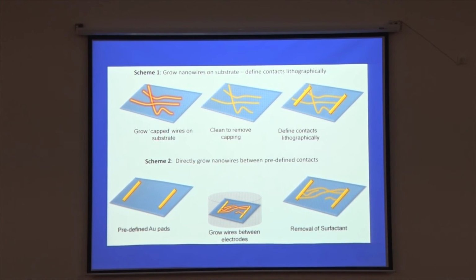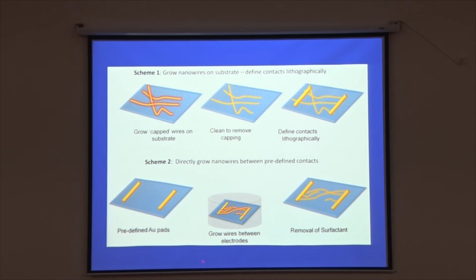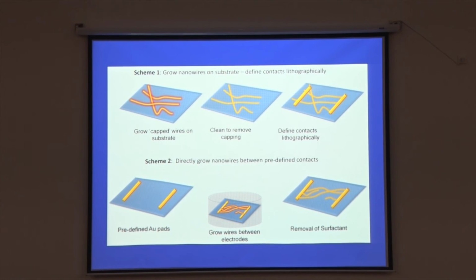But if you think about it, the standard lithography procedures that we would use would mean that you would actually see the wires and then make contacts. It's extremely difficult in this case. Even for things of the order of 100 nanometers, we know that lithography and site specific contacts are not easy. So what we did is invert the problem, namely we make the contacts first and then grow the wires between the contact pads. We can do this because we know that it happens by particle-particle attachment, as I explained, and therefore the gold clusters can attach to this contact pad and then grow, and since there is another pad close by, they can span across.